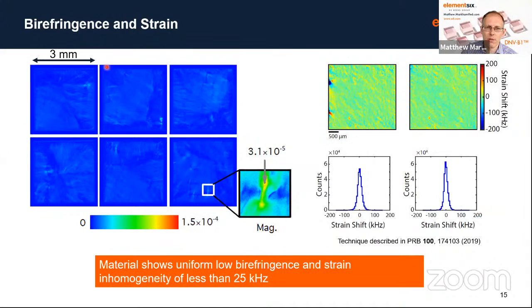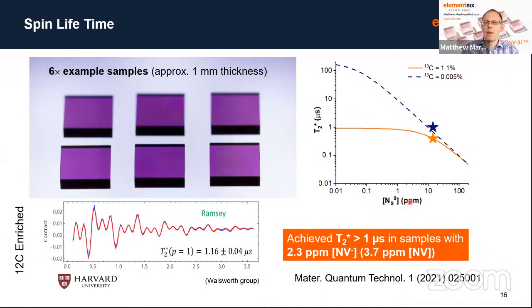So these are 3 by 3 millimeter samples, and they were able to then map out this strain and plot this up, and showed that we have less than 25 kilohertz line width variation, which basically, in this plot here, means that on that plot I showed you earlier, we are at the limit of where you'd expect to be for the spin lifetime. And the samples you get are these nice purple color. So these ones, the T2 star of carbon-12 enriched ones are around a microsecond.